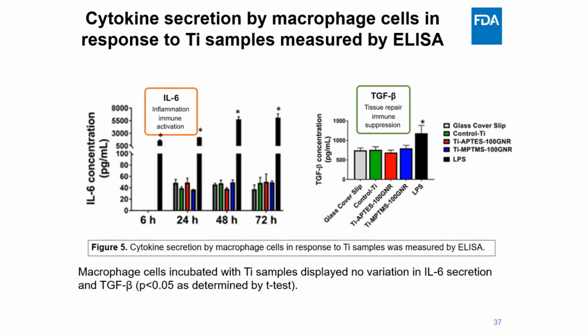In contrast, we have also used a positive control, which is lipopolysaccharide, or LPS. It produced a strong cytokine response, confirming that the assay was functioning as expected. So this finding indicates that the GNR-coated titanium surfaces appear biocompatible, at least in terms of macrophage activation.